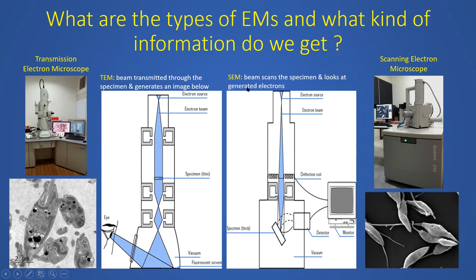Whereas in a SEM, it is completely different. So what happens here is the electrons are not transmitted through the specimen. What happens is the electron beam interacts with the specimen. The specimen is here, the electron beam, the blue path that you see, interacts with the specimen. And as a result of this interaction, different signals are generated. Different electron signals are generated with different energies, low energy electrons, higher energy electrons. So these are all collected by various detectors. We'll discuss them in detail later. So we have different detectors for collecting these signals. And the signals are processed in the computer. And you can see the image on a monitor or a computer. You cannot see this image using your eye, nor can you use a camera like for a TEM, right?